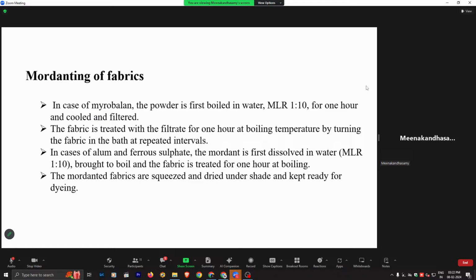The slide shows the mordanting of the fabric. First, I took three types of mordant: myrobalan, alum, and ferrous sulfate. The myrobalan powder is boiled in water for 1 hour, cooled and filtered. The ratio was 1:10. The fabric is treated with the filtrate for 1 hour at boiling temperature, turning the fabric in the bath at repeated intervals.